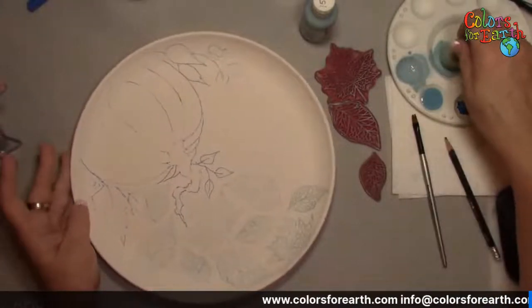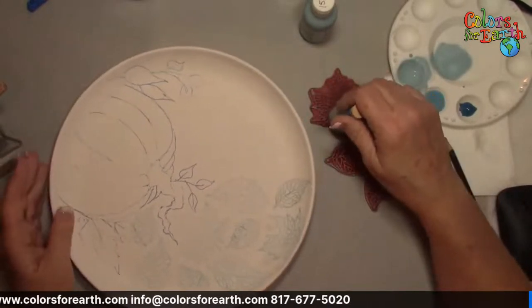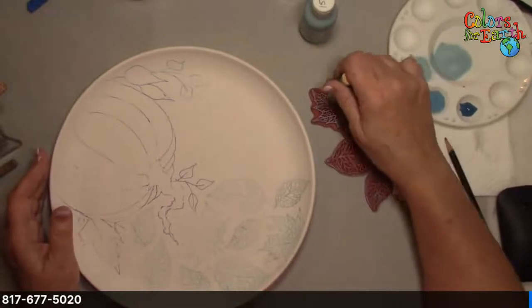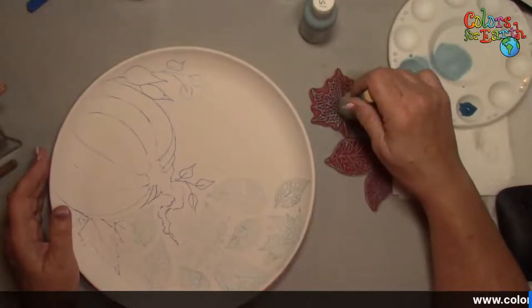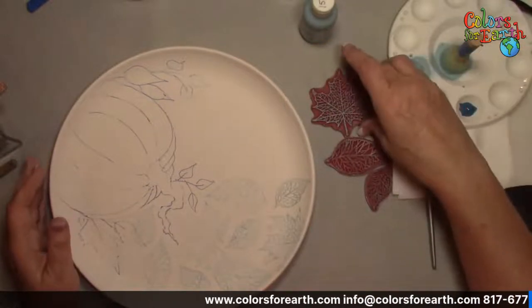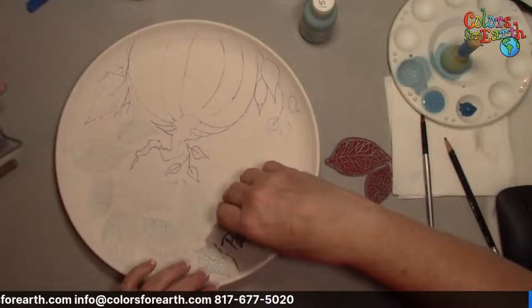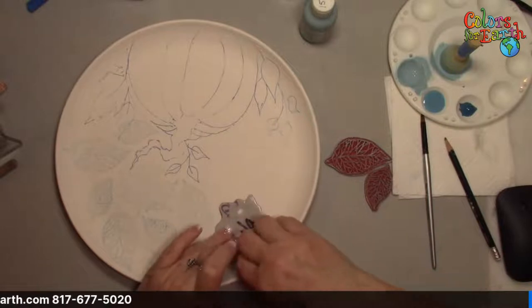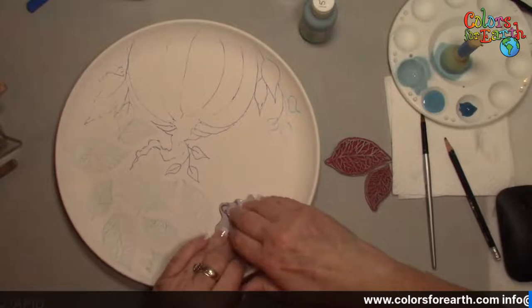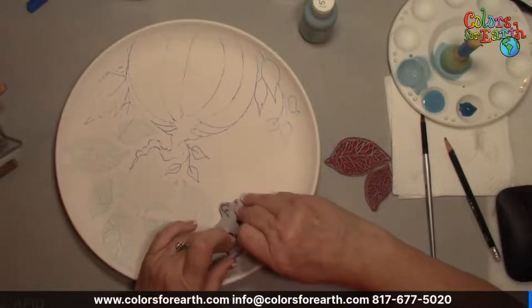These are color concentrates — translucent underglaze made for greenware and bisque. They will go to cone 5, cone 6, or lower firing earthenware, which is 04/06. Some colors change a little bit — pinks and purples tend to burn out at cone 5 and cone 6. So go to your color stroke pinks and purples; those will hold at that temperature.